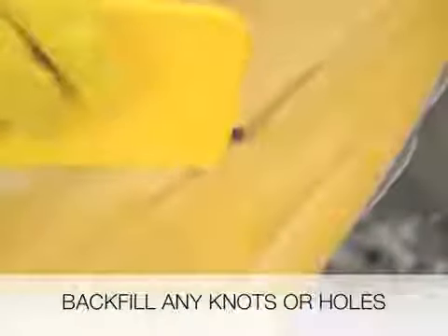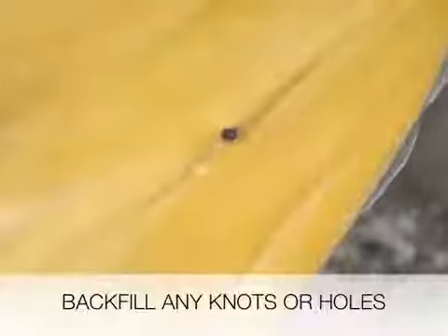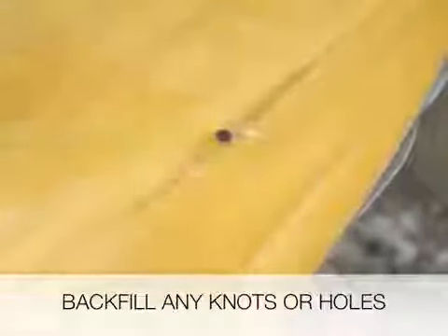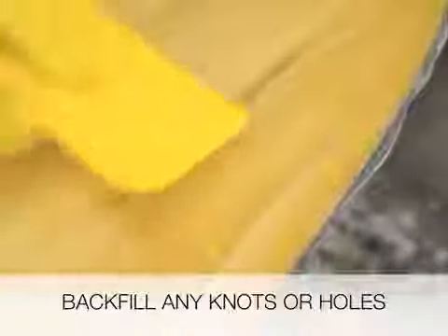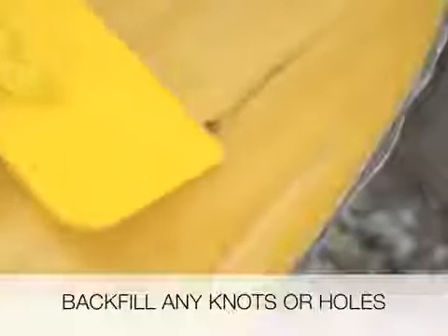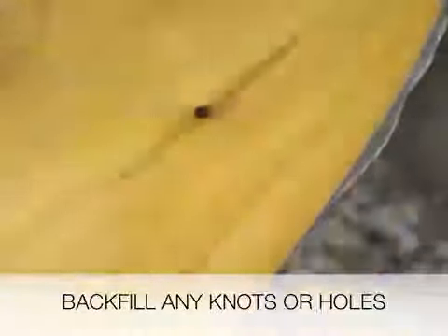When laminating wooden surfboards, knots and holes in the wood grain can sometimes pull in resin, leaving behind air bubbles that will get trapped in the fiberglass. Be sure to backfill any knots or holes with resin before the lamination has set. At 72 degrees Fahrenheit, CLR resin with fast hardener will usually give a tack-free time of 3 to 3.5 hours.